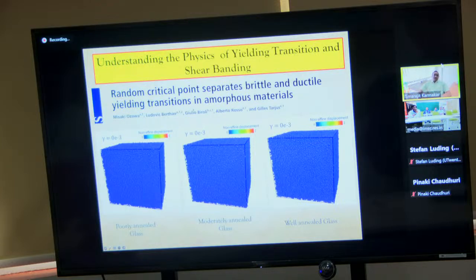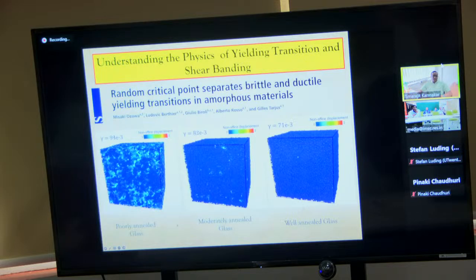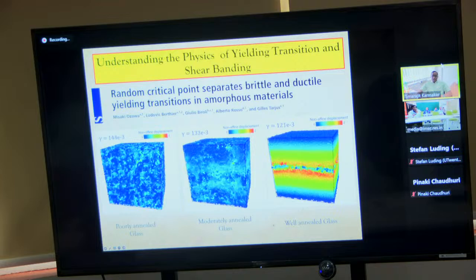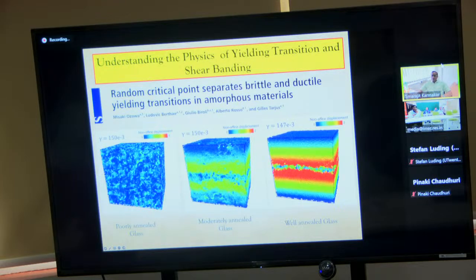And what people looked at is basically these glasses, which are called ultra stable glasses. So I'm basically clicking the three movies. The extreme left one is for a poorly annealed glass, and you see that there are a lot of plastic events happening in various parts of the sample. And the middle panel is a moderately annealed glass, which you can achieve even with simple molecular dynamics simulations. But on the extreme right, you have a well annealed glass prepared with swap Monte Carlo.